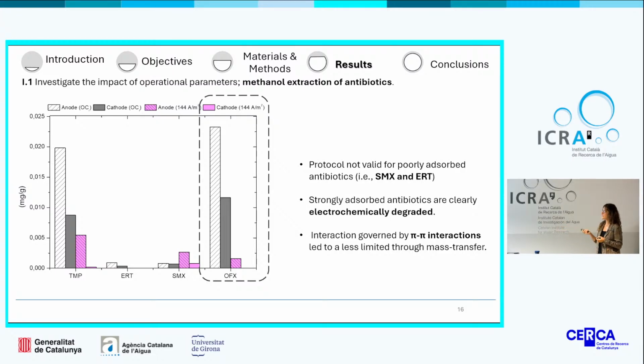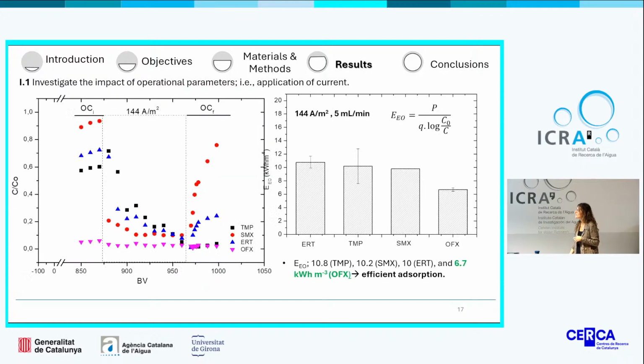According to the result, we could observe a significant difference between the concentration of ofloxacin in the anode during the open circuit condition and in the cathode during the open circuit conditions, compared to when they were anodically polarized, confirming that strongly adsorbed antibiotics are clearly electrochemically degraded. And also the importance of the strong π-π interactions, which reduce the mass transfer limitations and therefore favor the electrochemical oxidation of contaminants.